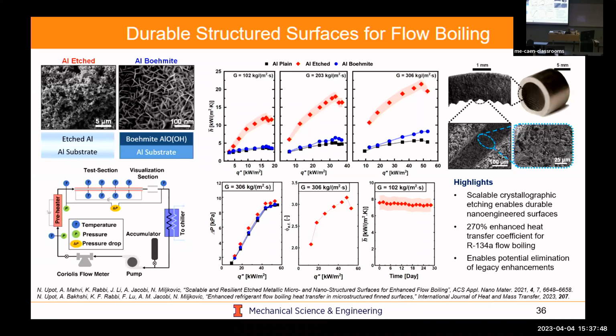And so one piece of work which we've done is looking at refrigerant flow boiling. This is the heat transfer coefficient for these etched surfaces as they compare to a plain or a boehmite surface as a function of heat flux for 3 different mass fluxes. And what you'll see is about a 250 to 300% increase in your heat transfer coefficient just by pre-processing your tube by this etch chemistry, which is HCl in this case.